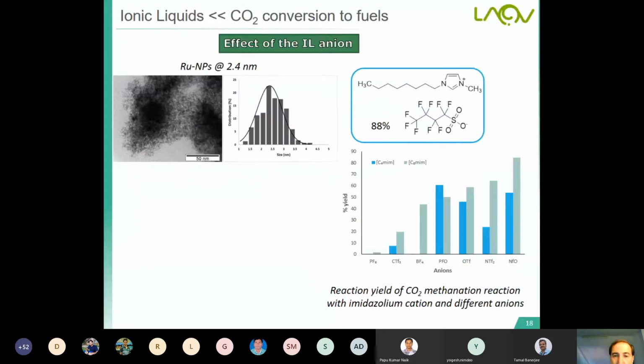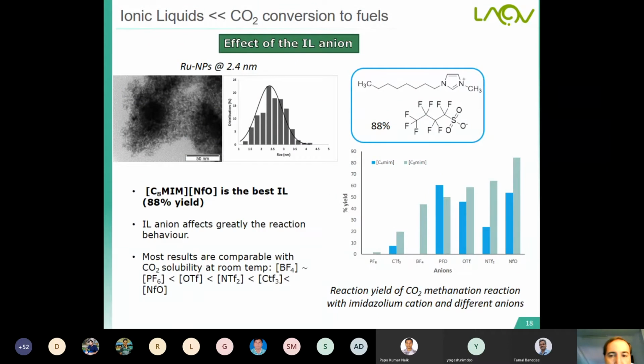But the effect of the ionic liquid anion is very important for this. Why? Because we need to use hydrophobic anions, fluorinated anions, and the ionic liquid anion greatly affects the reaction behavior. We prove that the best anion for this is this sulfonate fluorinated anion, and we obtain 88% yield using this system, this ionic liquid. This anion is named nonaflate, and it is the best ionic liquid for the reaction.